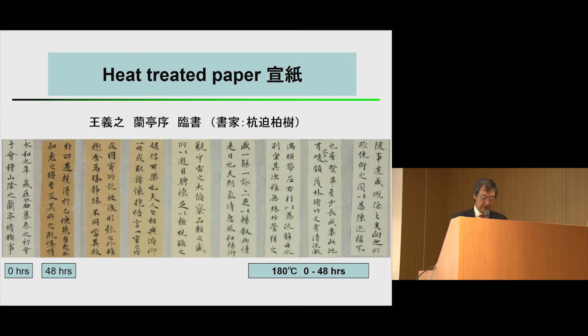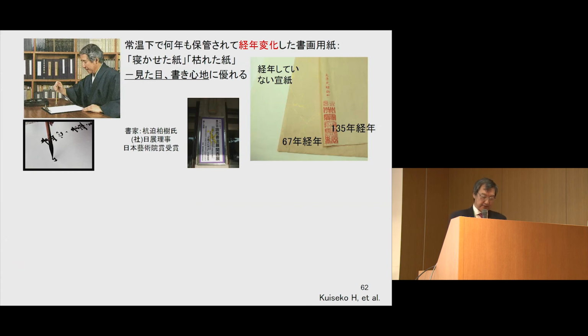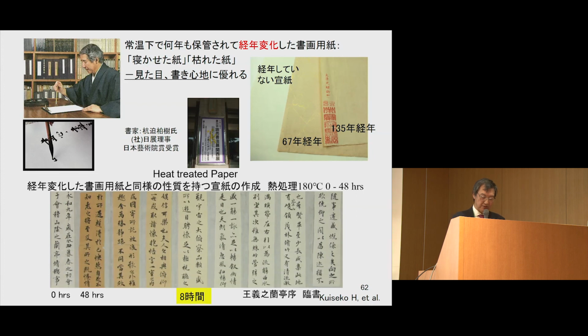And also, at the same time, during such a heat treatment, adhesives are also degraded. So carbon ink has run and spread by the heat treatment. So in collaboration with the famous calligrapher, Mr. Kuiseko, we found it best in the treatment of 8 hours at 180 degrees Celsius, both in color and paper, and the penetration of the carbon ink from an authentic point of view.